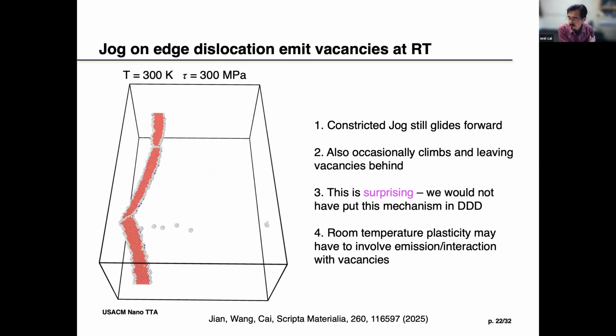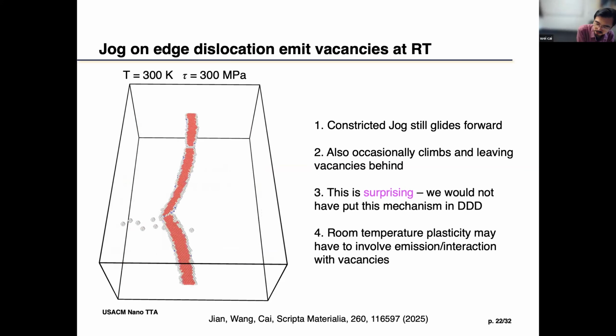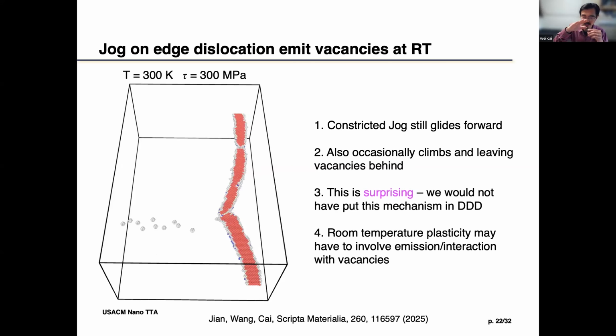In BCC, there are a lot of screw dislocations, and a screw dislocation will do that, because if you have a jog on a screw dislocation, that jog literally cannot move other than by emitting, okay? But this is an edge dislocation. So the Burgers vector is going horizontally, and everybody is able to move horizontally. That's why it was very surprising for us. There's no reason, if it just moves to the right, for them to emit vacancies, but it decides to climb along the dislocation and emit vacancies. That's why it's surprising, because usually we associate this kind of thing with a jog on a screw dislocation. Okay. Thank you.